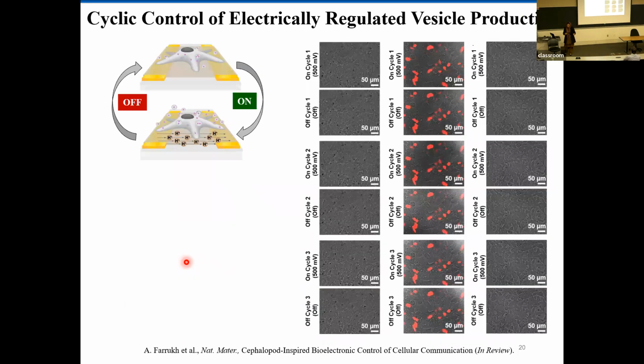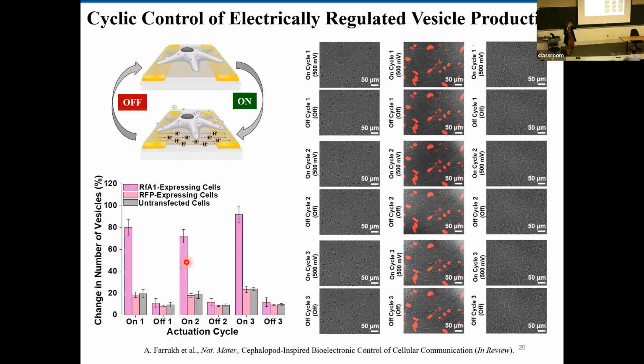Then comes the part that is only relevant if we can have this control over multiple cycles. If we can only produce vesicles once with electrical actuation, it is interesting, but not very applicable. So we wanted to see if we can have this control over multiple cycles. All of our cycles are 2 hours: 2 hours of on cycle, 2 hours of off cycle, sequentially. What we observe is that when we have an on cycle, we have a significant increase in the production of extracellular vesicles. When we have an off cycle, the production decreases.